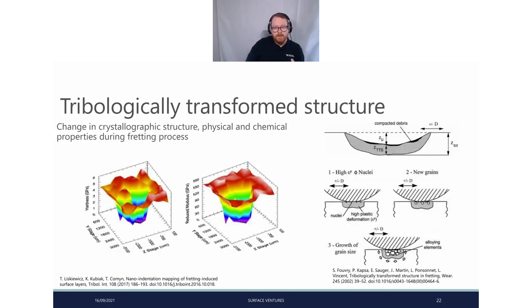And one interesting thing with tribologically transformed structure, there's been quite a few papers on this. Tomasz Liskiewicz on nanoindentation of fretting-induced surface layers. This is a very good paper. I would recommend that you take a look at that. It's performing fretting wear, but then nanoindenting and essentially creating a map of how the hardness and reduced modulus change in the fretting scar relative to the area around it. So there's been quite a bit discussed in literature surrounding, of course this transforms, but